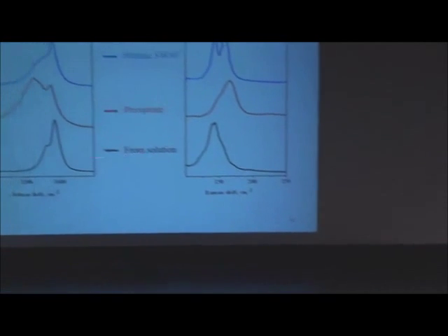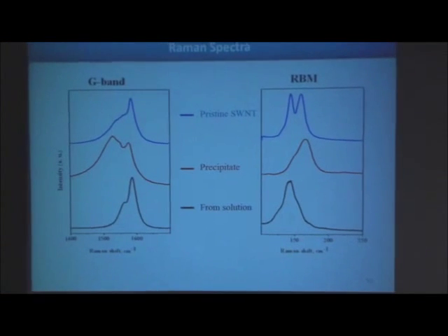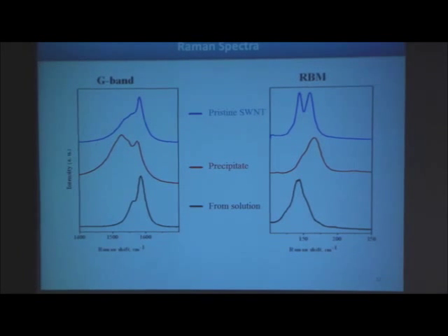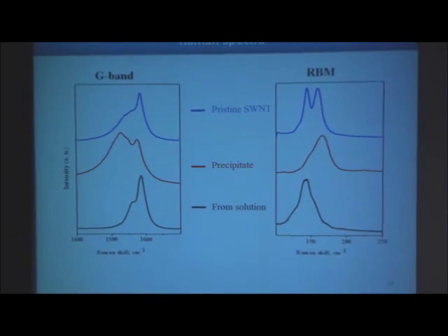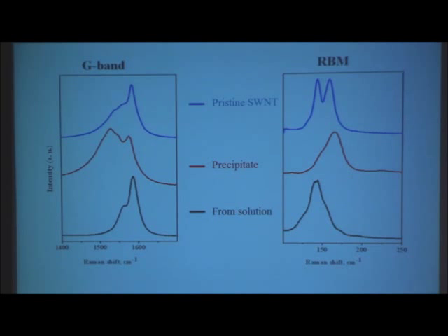And you can also see in the Raman band. Raman band pristine has a mixture, but the precipitate has mainly metallic species. From solution, only the semiconducting species. This, I think, is a fantastic thing for an old man like me, because you do a simple reaction like that and give you, people have been trying to do this for so long. It's a very important engineering application here.